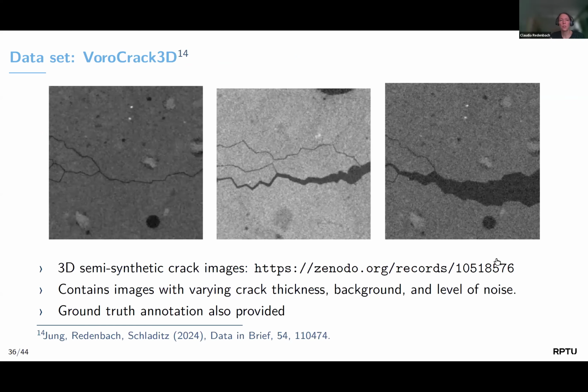We also published a data set. So if you're interested in using such images, there is VoroCrack 3D, which is a data set where we have simulated cracks of different widths, different variability of thickness, branching, different amount of noise added, also different concrete backgrounds that now could be used for such segmentation studies. And that's available on Zenodo.